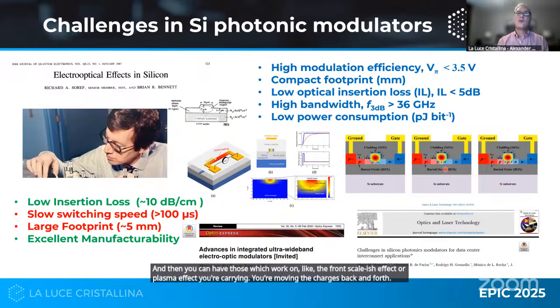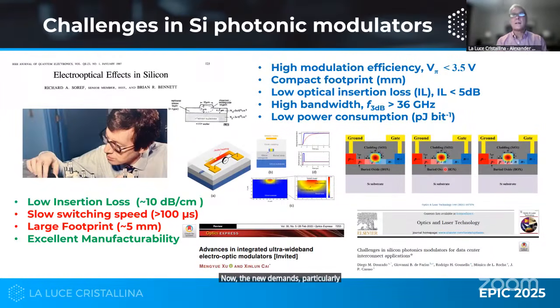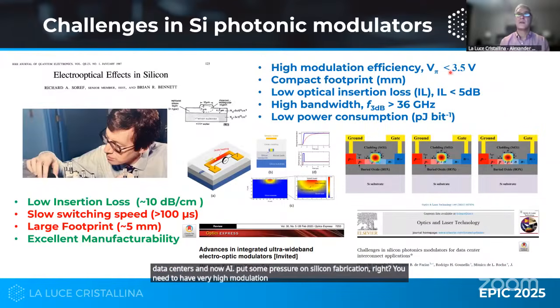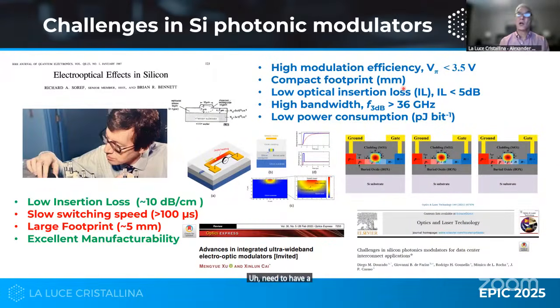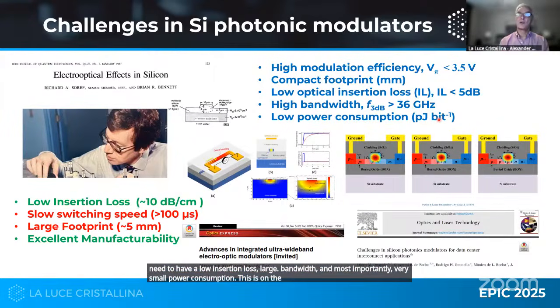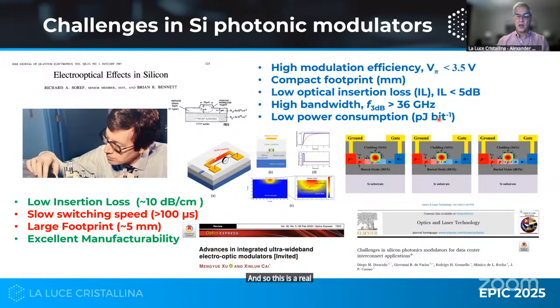Now, the new demands, particularly after COVID, on network traffic, data centers, and now AI, put some pressure on silicon fabrication, right? You need to have very high modulation efficiency, V-pi below 3.5 volts. They have to be fairly small, need to have a low insertion loss, large bandwidth, and most importantly, very small power consumption. This is on the order of picojoules per bit. And so this is a real challenge for silicon.